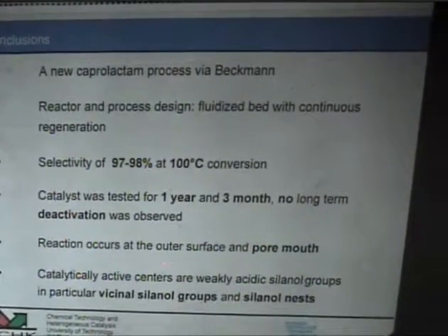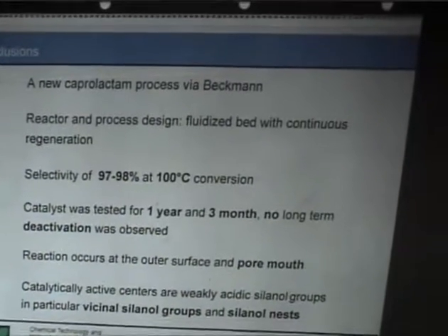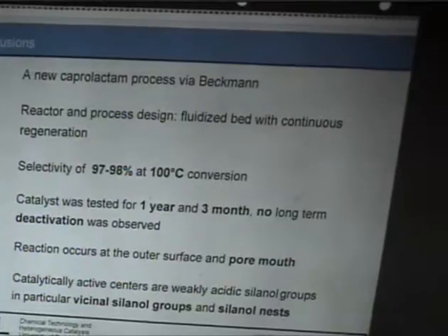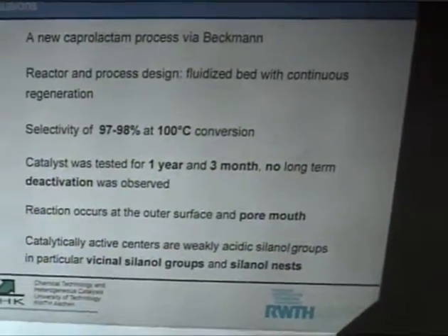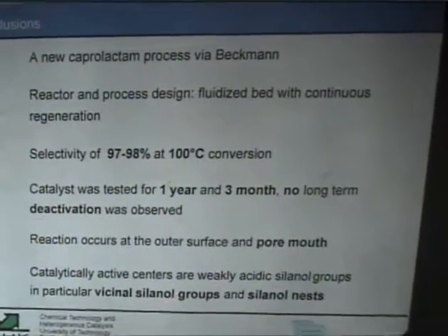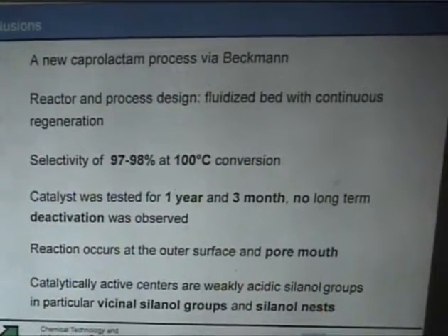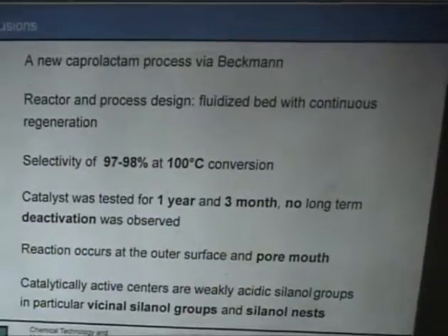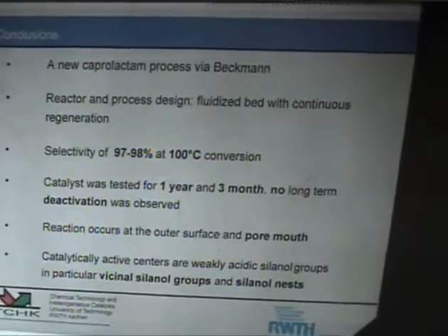We found that the reaction occurs at the outer surface and at the pore mouth, and furthermore, we also characterized the active sites, and the active sites are silanol groups, and silanol nests. That means extremely weakly acidic sites. The reason for that I don't want to go into detail now, but you can come to the Catalysis Club tomorrow evening in Philadelphia, then you will hear that.